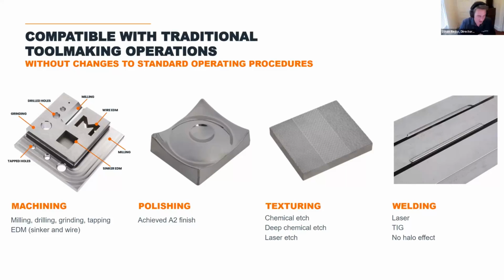deep chemical etching. And they're going to be able to be repaired the same way a traditional tool will be repaired. Laser, TIG welding, you don't see those halo effects. So you can see an example there. We cut out a notch of a tool, we rolled it up, and then we went across and ground it, and it looks the same way a traditional tool would look. So if you do need to do repair, absolutely can be done without any changes to your standard operating procedures, which is really, really important to know.